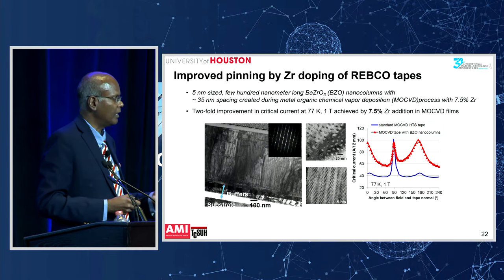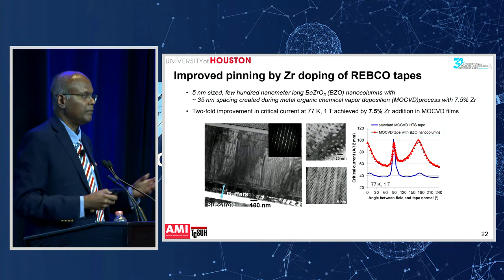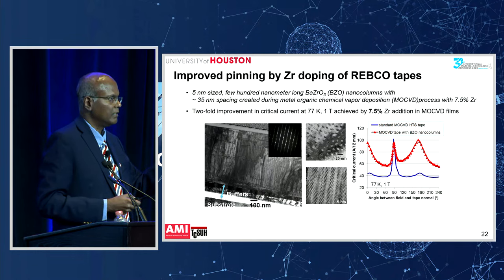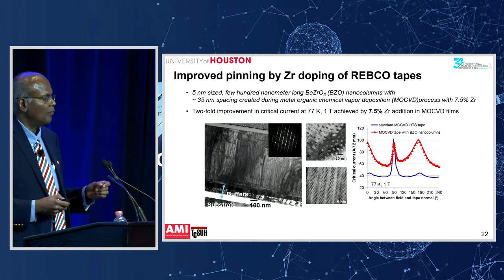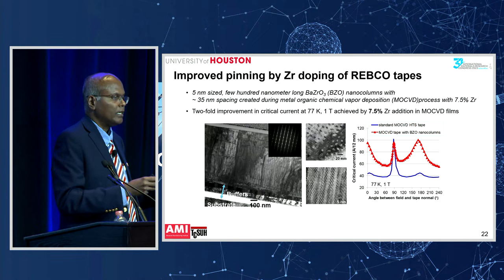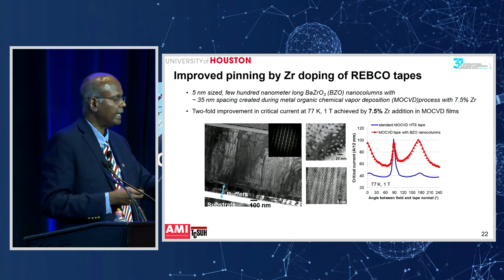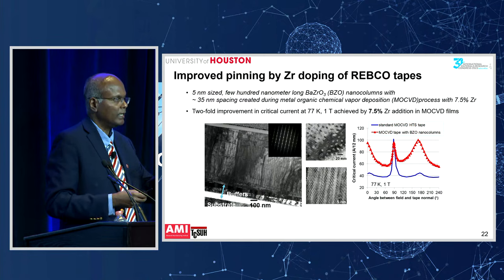So I'm showing a cross-section of a superconducting film, which is 1 micron thick, made by MOCVD, and it's an epitaxial film. Like I said, you see the buffer layers in there, and the flexible substrate is below that. While we are growing this epitaxial film, we add some zirconium to the precursor, and when you do that, you form these barium zirconate nanorods, or nanocolumns, and you can see that in the high resolution microscopy on the cross section, and in the plan view, you can see the circles. Those are actually the size of these nanorods.